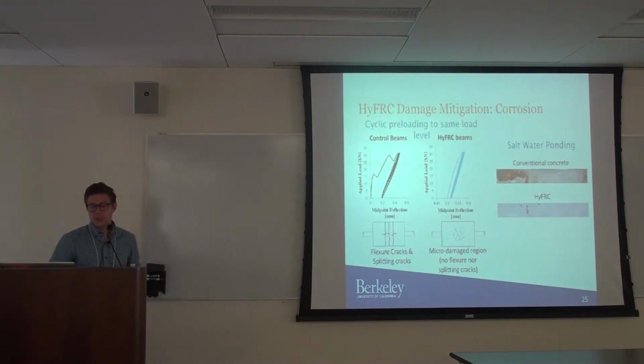As far as corrosion, there were several long-term corrosion tests. These were natural corrosion instead of accelerated, where beams were pre-cracked and salt water was ponded and just allowed to naturally corrode over the course of several years. In the initial pre-cracking, you could see that in conventional concrete, the normal crack pattern allowed that salt water to penetrate much more than in the HyFRC. You don't get quite as large cracks, so you don't get as much penetration.